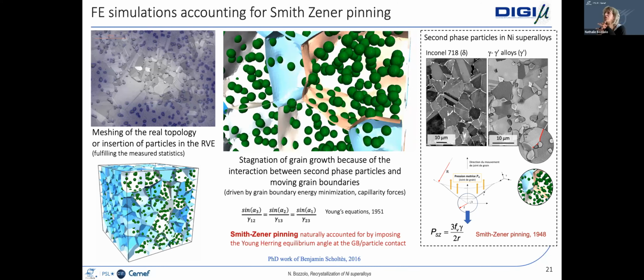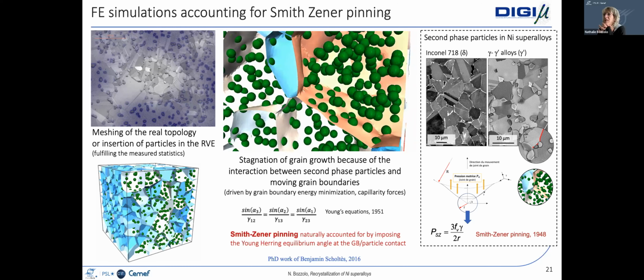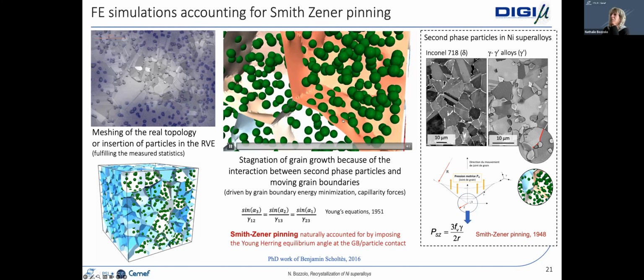So here, for instance, we have no stored energy. Then the microstructure is evolving only because of the capillarity effects. You can see the interaction of the second phase particles with the boundaries. And after some time, grain growth will stagnate. A kind of equilibrium is achieved because the driving force for making the boundary migrate is no longer strong enough to counterbalance the pinning forces. And this is where you end up with a limiting grain size, which is also described in the mean field model of Smith-Zener.